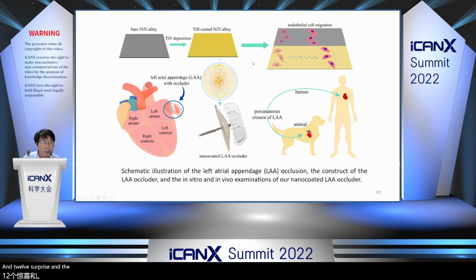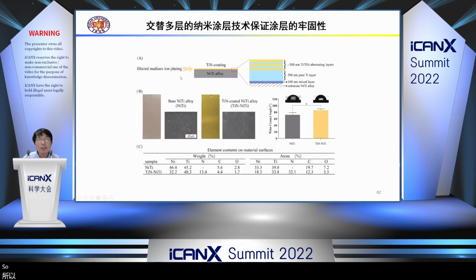And to our surprise, we found for the first time that the human umbilical vein endothelial cell can migrate much faster on the nano-coated surface. We then, in cooperation with some companies, fabricated the left atrial appendage occluder, and also we examined its efficacy in animals, and then we did the clinical trial and applied it in the human body. If one simply coats the titanium nitride on the metal, it is not stable. So we invented an alternating layer. In this way, the surface modification could be quite stable, but the outermost layer is always the titanium nitride layer.